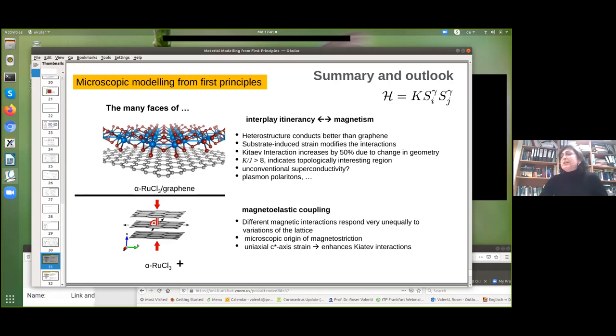In the second part, you are doing exactly the same. Even though I apply uniaxial pressure along the Z direction, what happens is you apply pressure, and this just blows up along the A and B direction. You conserve the volume. Yes, exactly. And the difference between these two cases is that this one is more homogeneous because you are basically guided by all your substrate, while in this one, because you are applying uniaxial strain, you will have directions. One direction will be more affected than another direction.